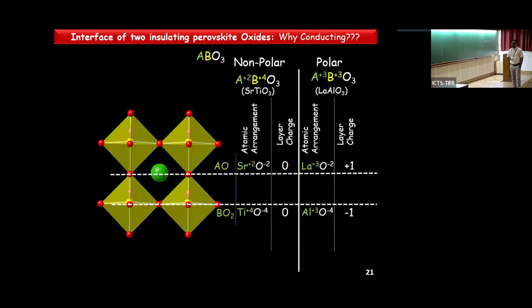To understand this simple structure, which Didi has already talked about, to understand the idea of this polar catastrophe, one can categorize perovskite oxides into two types: one is non-polar and another is polar. If you take strontium titanate and look into each layer, this layer is titanium +4, oxygen -4, so this is charge neutral, and this is SrO +2, -2, so this is also charge neutral. So this is known as a non-polar material.